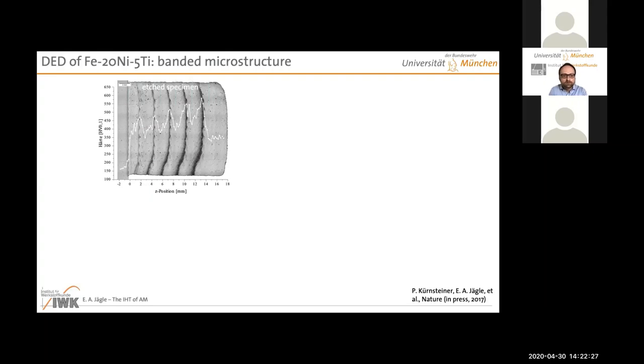But okay, what is it? What you see in the etched specimen is dark layers and bright layers. This is a constant composition, so no graded specimen. This is always 5% titanium. And if you look at the hardness profile, you see that it has a relatively complex shape. It has these peaks always when we have a hard, dark layer. And also we have a slight overall increase as you go to the top. But then at the very top, it drops down to some base level again. So quite complex. And it took us quite a while to understand what is going on here.